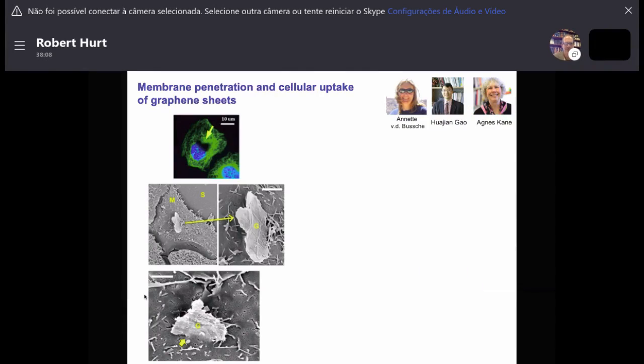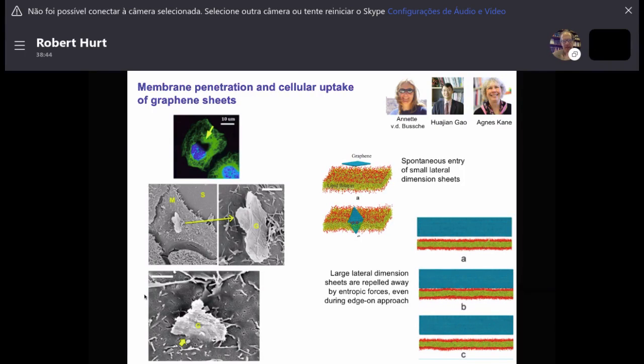We did some work just a few years ago trying to understand how graphene materials were taken up inside cells. And in this work, these are graphene microsheets, and we found them inside cells. This is my collaborator Agnes Kane in her lab. We find them inside cells. And it looks like if you try to capture the process while it's happening, as the sheet comes down, in the process of entering the cell, we often see the sheets standing up on end with their edges partially inside the cell and the rest of the sheet outside the cell. So it seems like they're entering edge on.